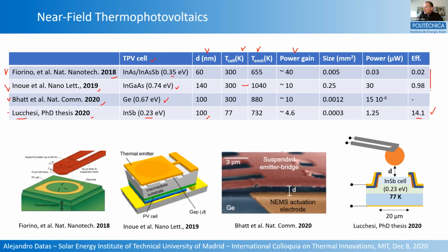But the rest of the publications are reporting very low conversion efficiencies for the moment. But I want you to pay attention especially to these two parameters, which are the size and the power that is produced by this experimental proof of concept. You see that the size is extremely small, so all devices are very, very small, and consequently the power that is produced in the near field is also very, very small.